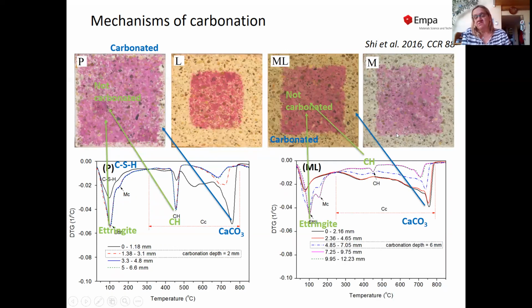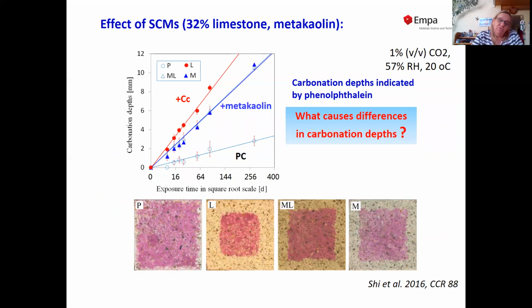The picture is basically similar for our metakaolin containing samples, except that we start with much less portlandite in the beginning. But again, we see the decrease of portlandite, the formation of calcium carbonate, the destabilization of ettringite and AFM phases. We can compare the progress of carbonation as a function of time. Again, we see that the Portland cement has a relatively slow progress, while the cement blended with 32% of limestone has the fastest, and the metakaolin samples are also relatively fast, but a bit slower than the calcium carbonate samples.